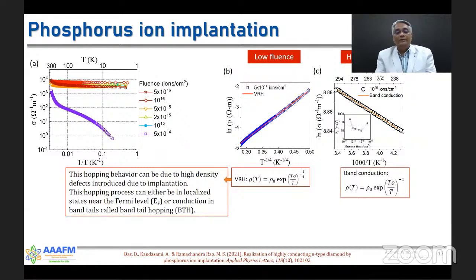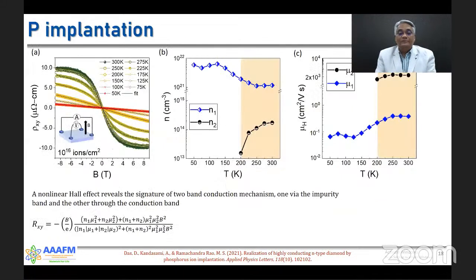The conductivities are significantly enhanced, but the highest conductivity is seen for 5 times 10^16 ions per centimeter square itself. But in the case of nitrogen, you have to go one order more of implantation fluence in order to realize the highest conductivity. And we could explain the conduction process, even in this case, similar to what we have in the case of nitrogen implanted UNCD films. A nonlinear Hall effect reveals the signature of two-band conduction mechanism, one via the impurity band and the other through the conduction band process.